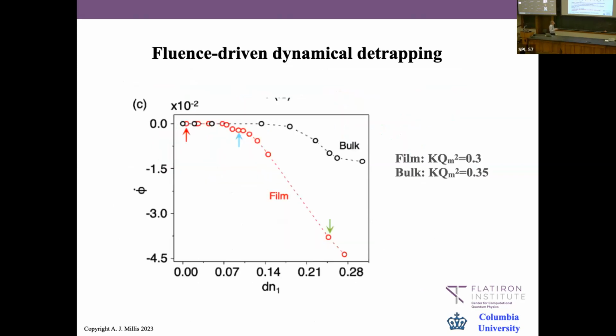So I can compare the slope to the strength of my initial pulse, parameterized by how many electrons got transferred. And what you see is that there's a clear break. It's different if you use the bulk material or a thin film, for the reasons I showed you before. It depends on the substrate. But there's clearly a region where the slope is within resolution zero, and then above a certain fluence, it breaks away in ways that are a bit different depending on the system.